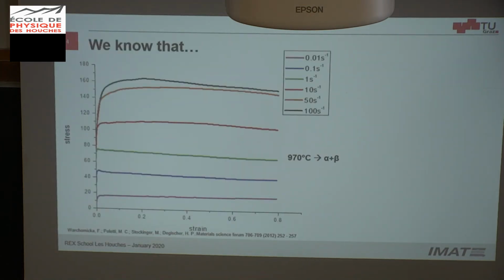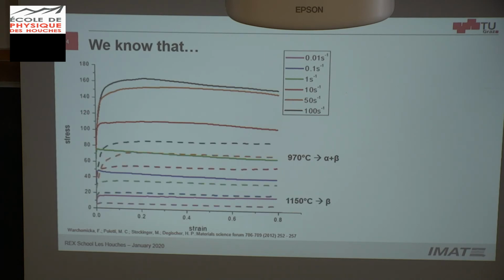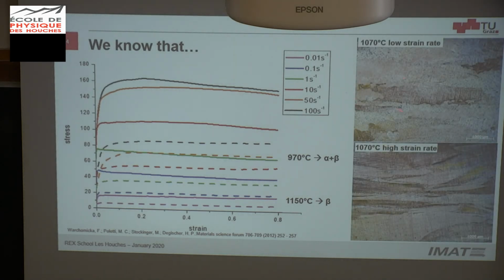Okay, let's move now to titanium alloys. In titanium alloys, we have this type of flow curves, which typically means dynamic recovery curves. For compression, this is at very small strains. Also, if we increase the temperature, everything goes down, and this is sensitive to strain rates. And we know that if we do deformation, this is titanium 6-4.